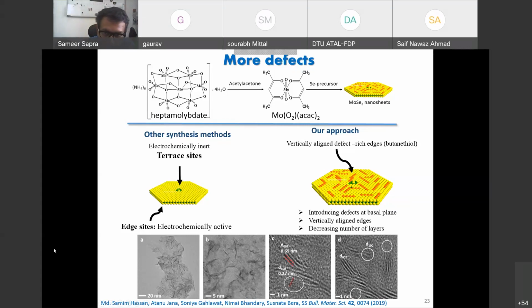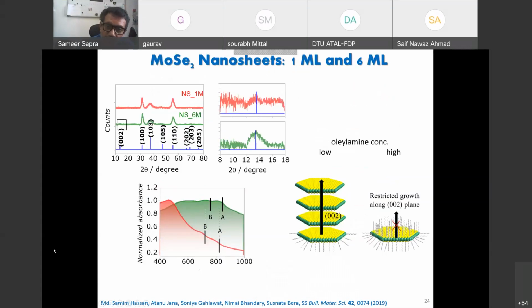Well, we can control the thickness of these sheets. In fact, here I'm showing you 1 monolayer and 6 monolayers. And if you look at diffraction, 002 happens to be the growth direction. And you do not see any 002 peak when you have 1 monolayer. Of course, you cannot expect to have diffraction with one single plane. But this is a collection of 20 scans. Actually, it's also very difficult to see with 6 monolayers in a single scan. So with a collection of 20 scans, you do start seeing something. It's very easy to control the growth.